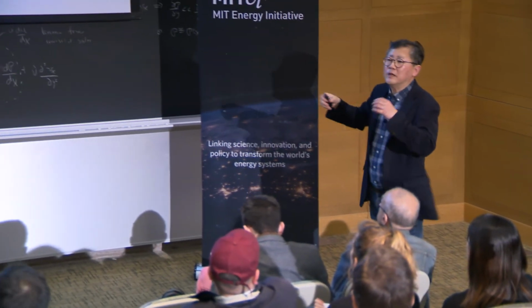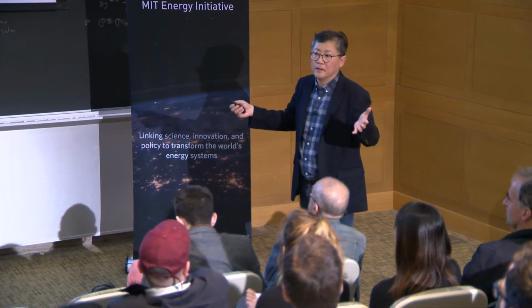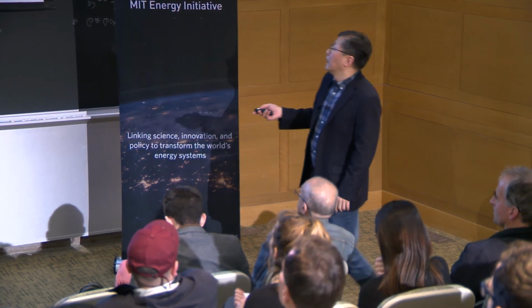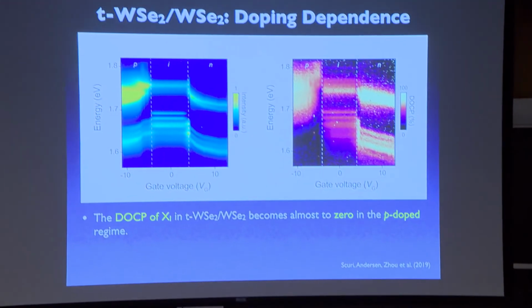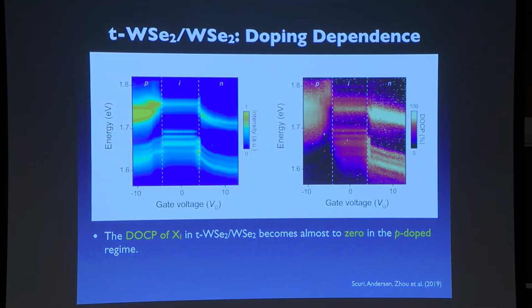But the more important thing is the following. When you twist them, you can start to introduce energy and momentum mismatch between two layers, which leads to different properties of those materials. And that can manifest itself as a difference in degree of circular polarization. The same is true. Actually, that twisting leads to different behaviors when you start to dope them using, for example, holes or electrons, and then how they behave in terms of degree of circular polarization. It turns out that that valley mixing, which leads to low degree of circular polarization, can be completely turned off by doping them with essentially holes or electrons.